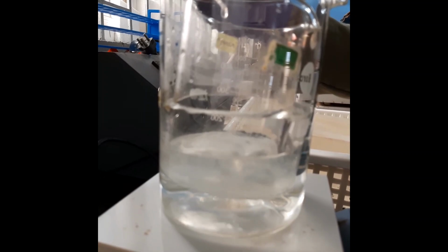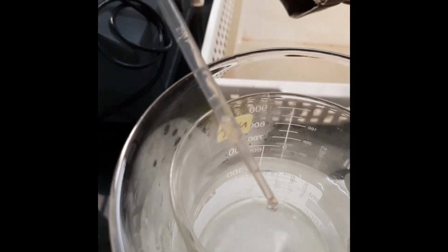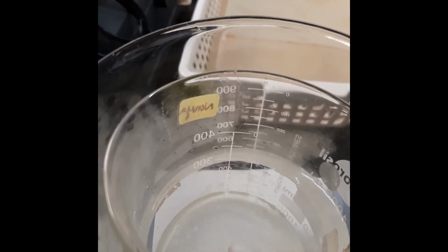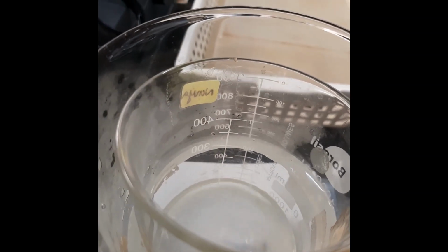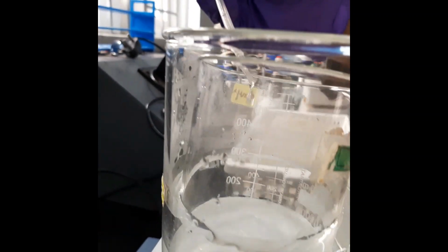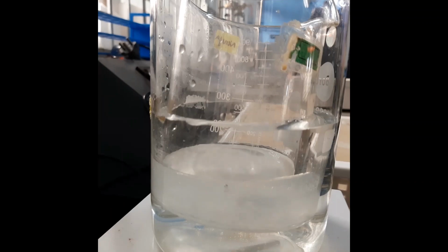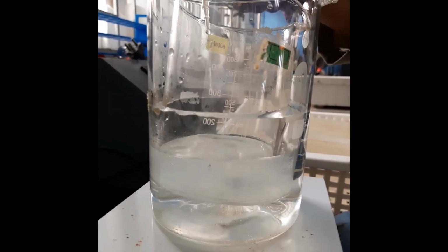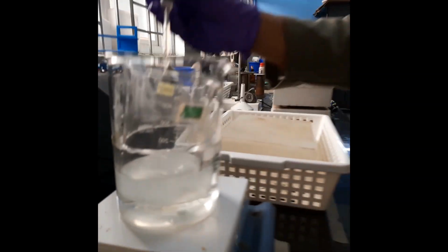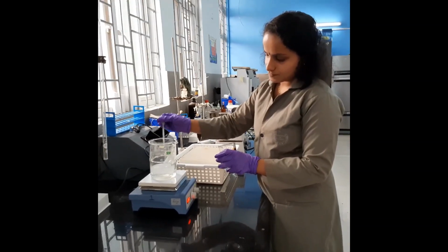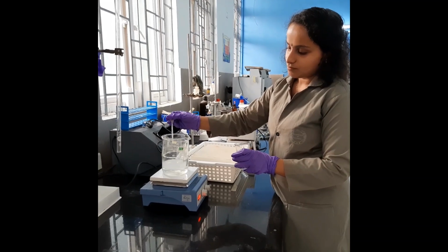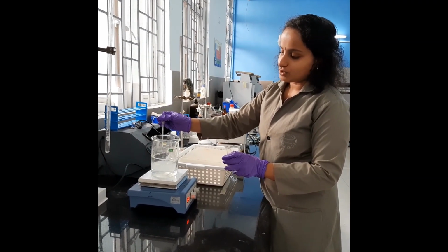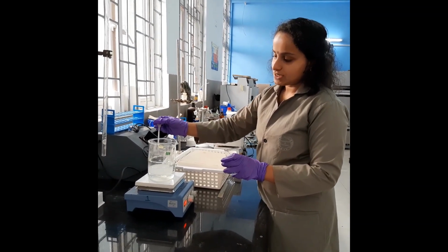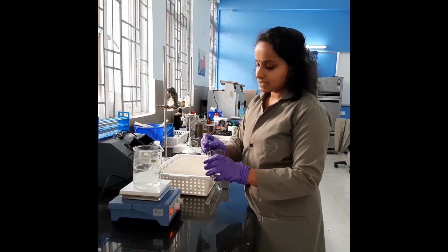So you can see slowly the precipitation started. Some white precipitates I can see in the beaker now. This magnesium and aluminum are precipitating as hydroxides. So it will form a jelly. You can see that initially. And after adding all this base solution drop by drop, we have to get a pH of around 8.5 or greater than 8.5 in our solution. Then only all our metal salts will precipitate as hydroxides.